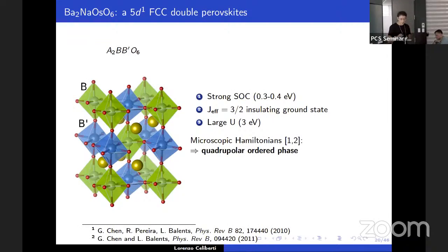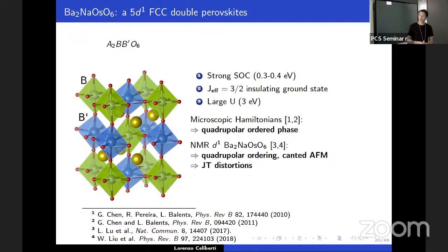This material presents a canted antiferromagnetic ground state, which from model Hamiltonians has been shown to be driven by quadrupolar interactions, so beyond the dipole-dipole interactions. And also NMR measurements show these complex ground states together with Jahn-Teller distortions. So there is a local distortion of the octahedra which shows reduced symmetry.